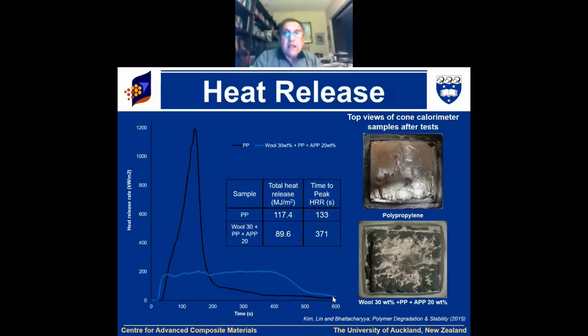I'm coming to that. What happens is that if you can form char, good polypropylene and wool, we form APP, which is an intumescent flame retardant. Like you remember those snake fireworks that you burn, and it will gradually grow like a foam. So it happens like that. There is also a foaming agent, and then it forms char. Because of the char, oxygen intake can get controlled and the fire can be put off.